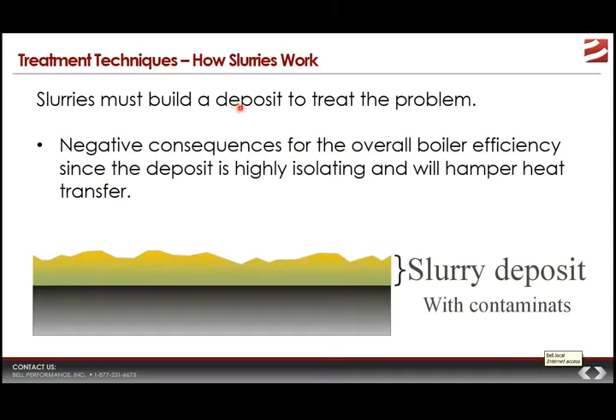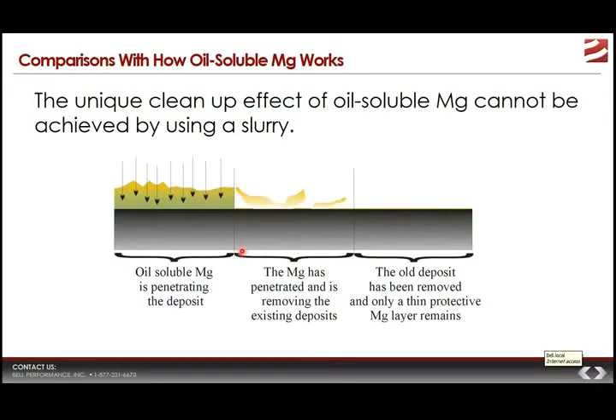However, because of the nature of how it works, you can run into a problem where if the deposit is too great, you can actually overly isolate or insulate the surface. And if that happens, you actually will hamper the heat transfer that you're getting, and that is not something that you want to do. Now, contrast that mechanism with how oil-soluble magnesium in ATX works.